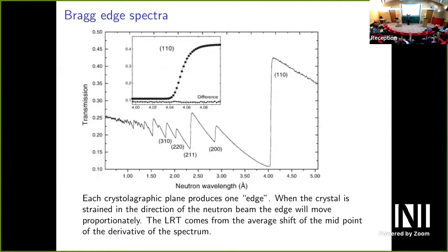So, all things being equal, you get a nice, clear, distinct jump for one of the more important crystallographic directions. And that tells you what the separation between those crystallographic planes is. Now, we get our sample and we apply some strain to it, and each crystal gets strained. Each little crystal is now a strain gauge, because when you squish it, the distance between the crystallographic planes changes depending on the component of the strain normal to that plane.